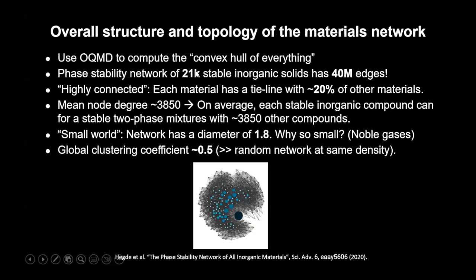And so just very quickly, I'm going to tell you a few things. One is that there's about 21,000 stable compounds on this convex hull of everything. There's about 40 million tie lines in this network. So it turns out to be a very, very dense, highly connected network. Every material in the network actually has a tie line with about 20% of all other materials. This means that as a network, this kind of materials network is much, much more highly connected than social networks and other things that network theorists tend to study.